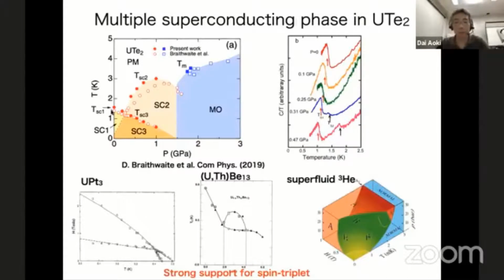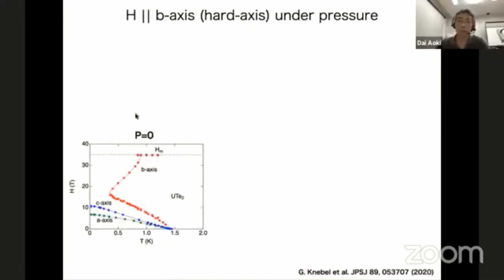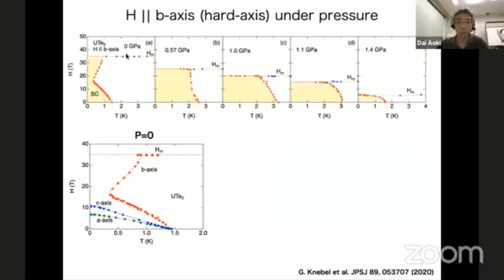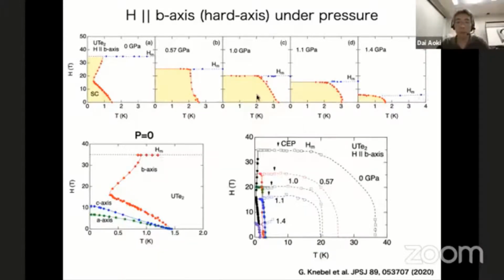So our interest is applying the magnetic field. What happened? Along the B-axis, the hard axis, we have HM, the metamagnetic transition. Applying pressure, HM is gradually suppressed like this. And then finally it collapses at 1.5 GPa, above 1.4 GPa. And the reentrant superconductivity is smeared and suppressed like this. But you can see here at the critical pressure the initial slope of HC2 is very large. So it indicates that at the critical pressure, fluctuation is very strongly enhanced. And also here, we had a critical endpoint at HM, and the critical endpoint is also decreasing like this. And then the fluctuation is induced.